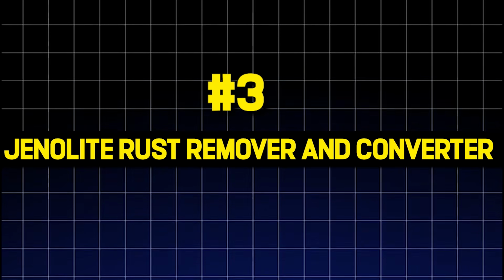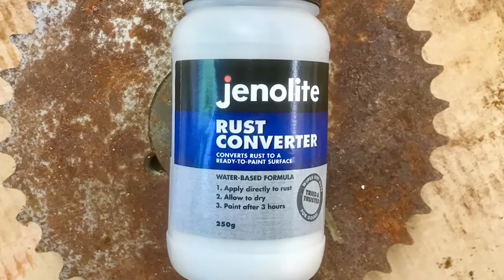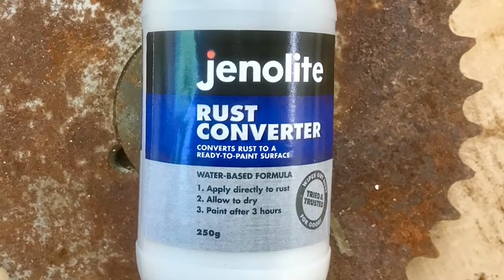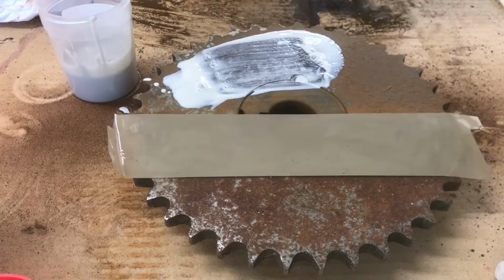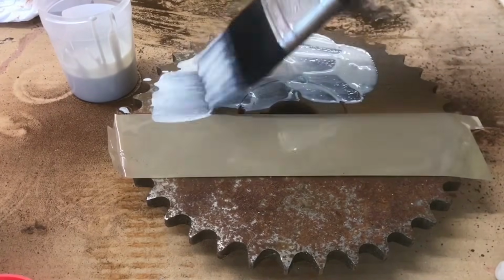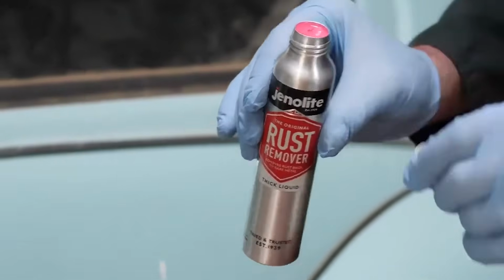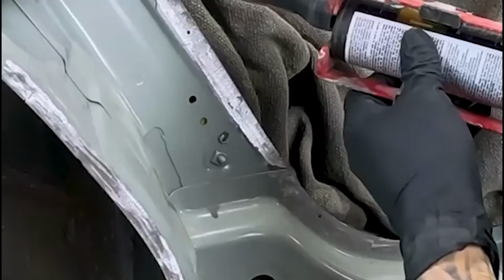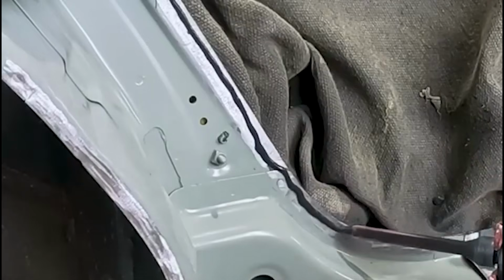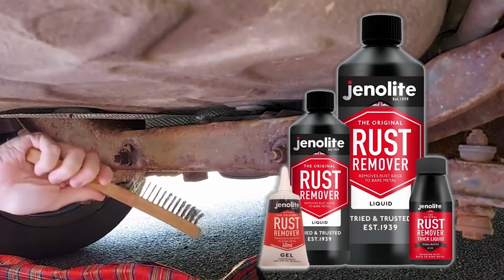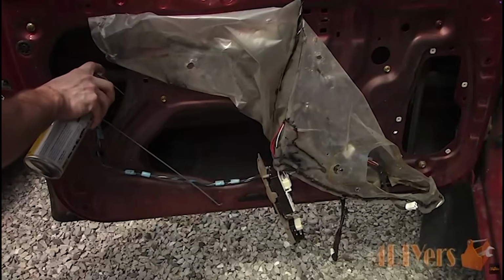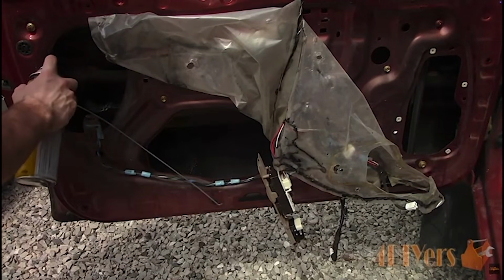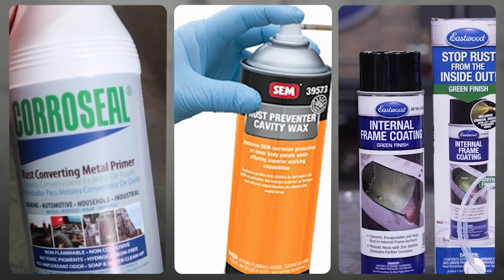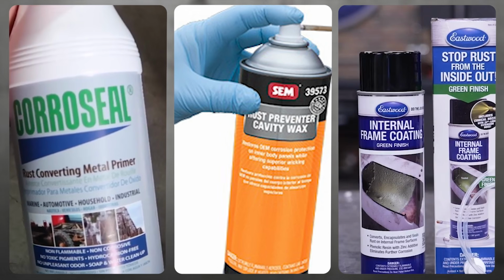Number 3. Jenolite Rust Remover and Converter. Jenolite is a British product with a long history in the automotive restoration market. It uses a phosphoric acid formula combined with a wetting agent chemistry that significantly improves penetration into tight rust geometry. The wetting agent lowers the surface tension of the formula. Lower surface tension allows the liquid to penetrate into pit surfaces and scale layer gaps that higher surface tension products cannot reach. This penetration characteristic is what puts Jenolite in the top 3 of this investigation.